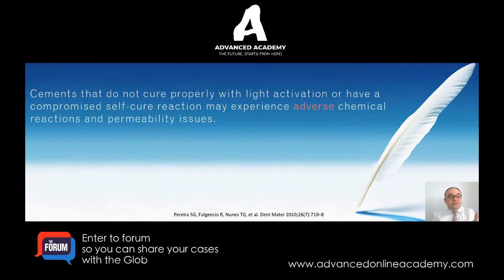That's why we see a lot of these dual cure cements sometimes debond. It is a problem that this cement probably did not set. It was either not stored properly or you didn't cure it properly. It did not set. You didn't have proper isolation. So before jumping to blaming the cement, we have to look at ourselves and look at what we are doing wrong before making any conclusion on the material that we're using.